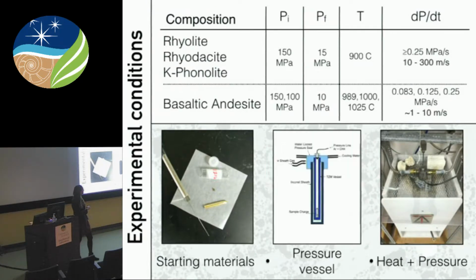Permeability analysis. The capsule was then put into a pressure vessel. It's actually sitting down at the bottom of this kind of T. At the top of the pressure vessel is a water-cooled region where the pressure line connects into. And the whole assembly is then lowered into a vertical furnace where it's heated and pressurized and left for an initial holding time, and then decompressed.